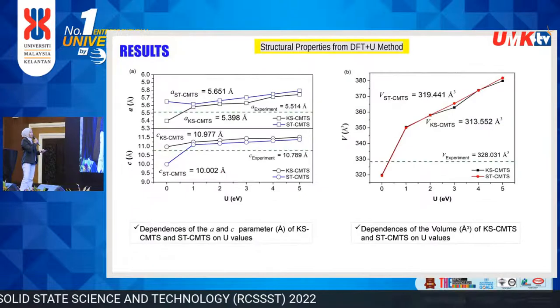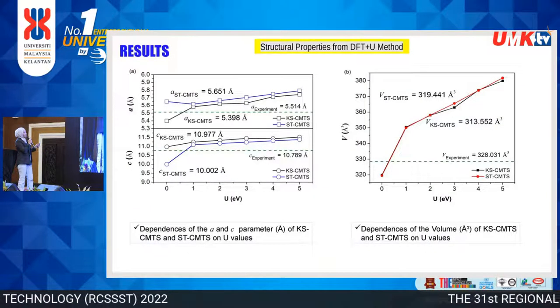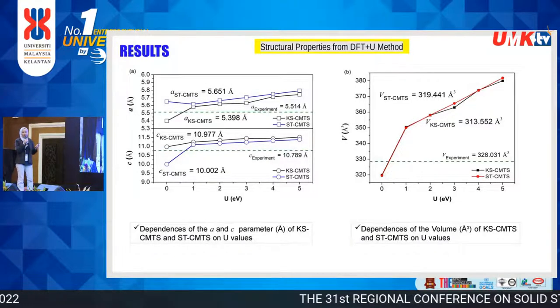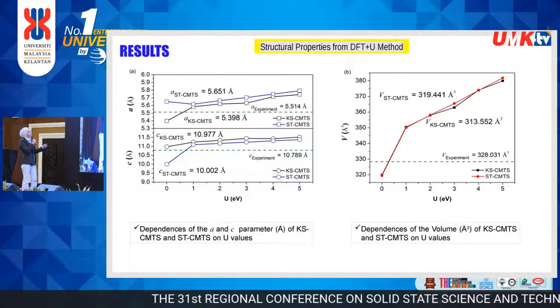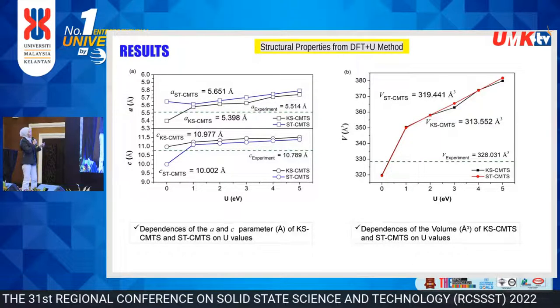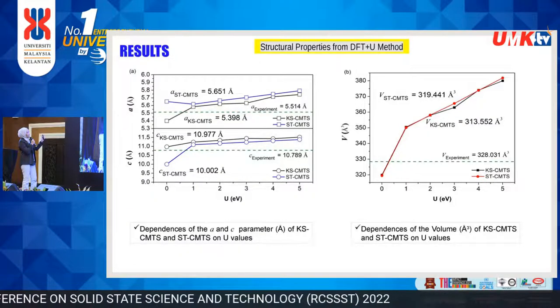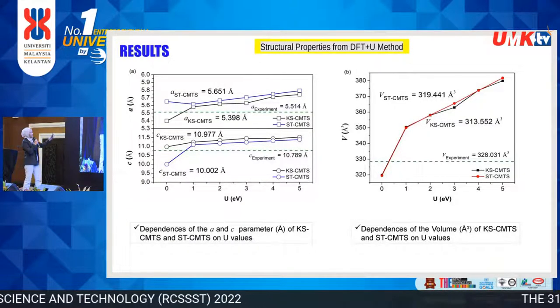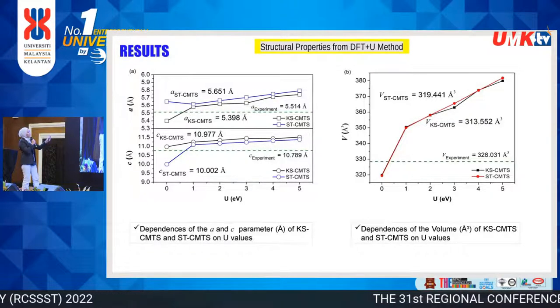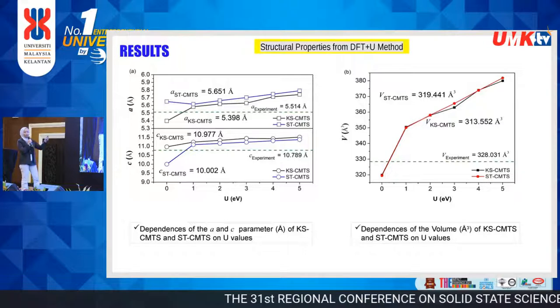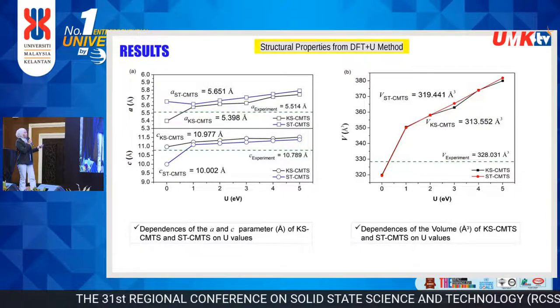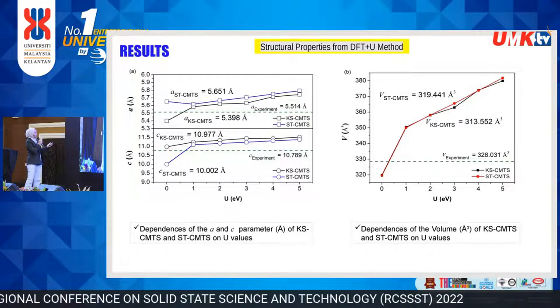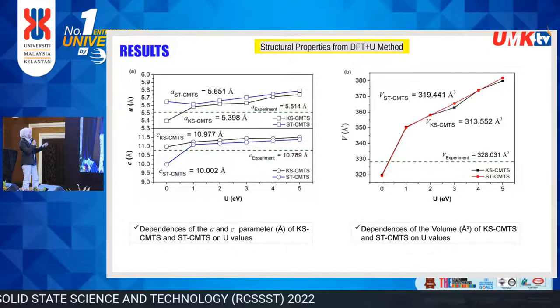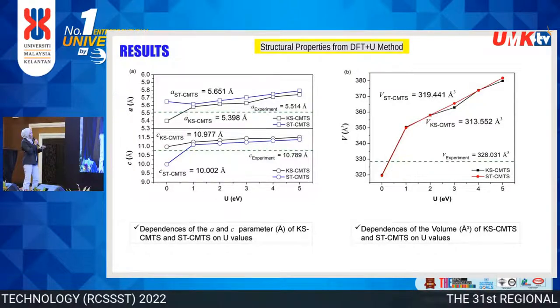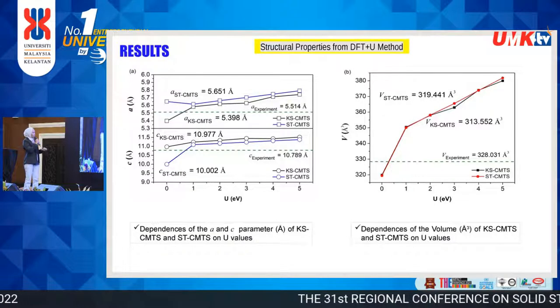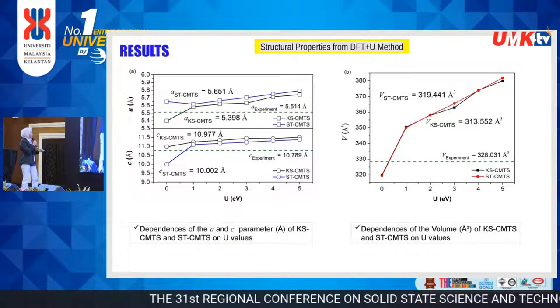Okay, next, this is the structural property from the DFT plus U method. As we can see here, this is the dependence of the a and c parameters and the volume when we add the Hubbard U to our structure. As the U value increases, the lattice parameter becomes bigger and moves further away from the experimental value. So we can conclude that the standard DFT is the closest to the experimental value.